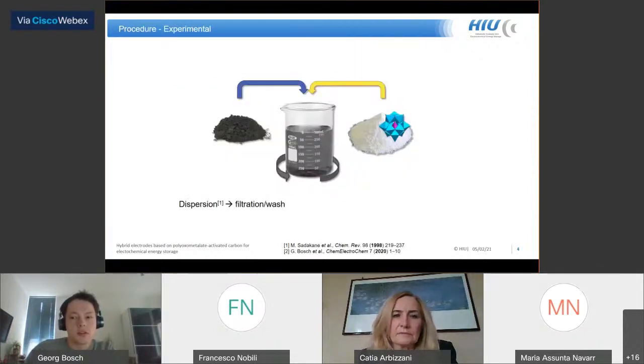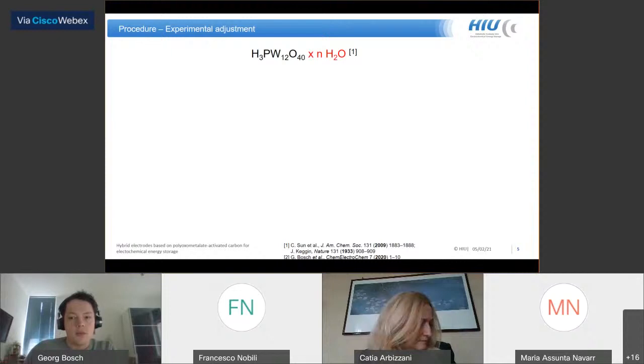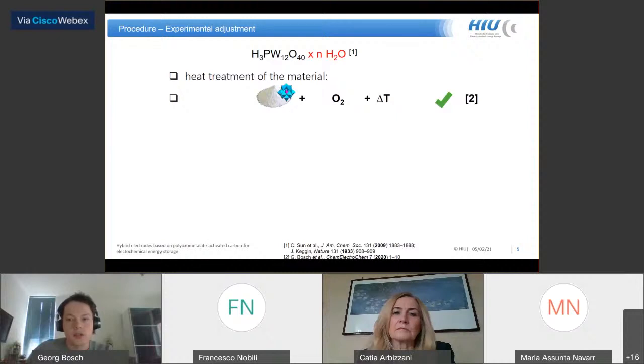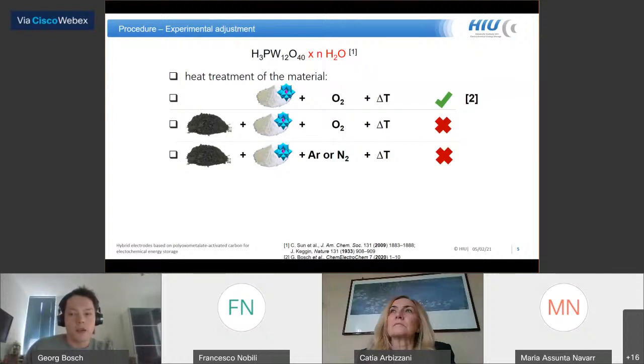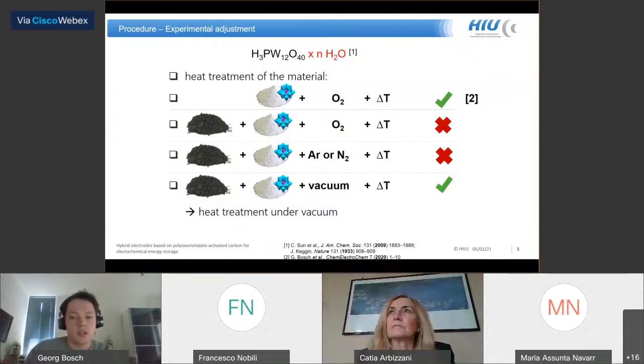The fabrication process consists of a repetition of dispersing, filtering, and washing, which makes it a simple synthesis. It is well known that polyoxometalates can include a high number of structural water and that this can have a negative effect on non-aqueous batteries. But due to the high thermal stability of the pure polyoxometalate material, it can be dried at air by heat treatment. The hybrid material consists of activated carbon, which will decompose by heating at air, but also heating with inert gases leads to a decomposition of the polyoxometalate cluster. This leads us to the treatment in vacuum, where activated carbon and polyoxometalate stayed unchanged.